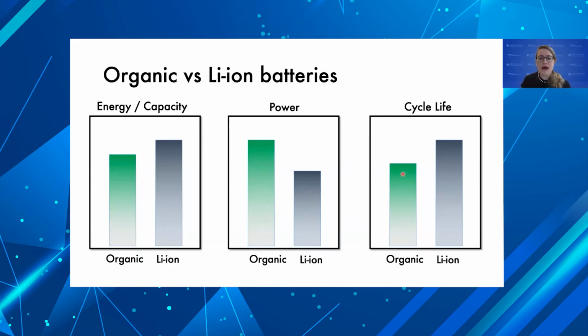However, the organic battery is still challenged by the low cycle life. The major problem is dissolution, and we'll see that come up again and again. So dissolution continues to be a problem. However, this can be easily solved with cross-linking or by picking the proper electrolyte. It's just something the field needs to pay more attention to.